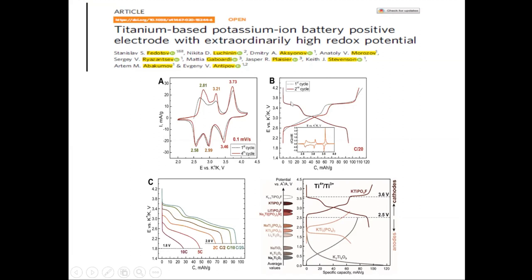capacity. But the other interesting thing is by going to this fluorine doping, so this is a titanium fluorophosphate material, he is able to raise the potential of this material to go beyond the potential where most titanates sit. And that's because most titanium materials are better anodes than they are cathodes. It's because of the titanium plus three to plus four redox transformation. But if you start to put in more electronegative elements, you start to raise the average potential of the transition metal, titanium in this case, and access the titanium 3-4 oxidation state.